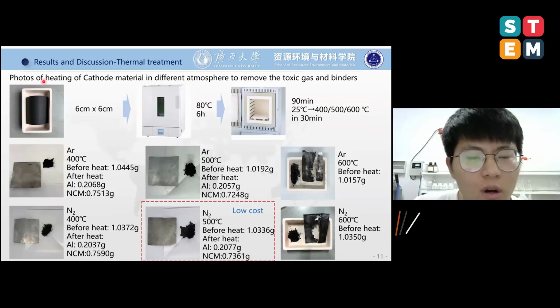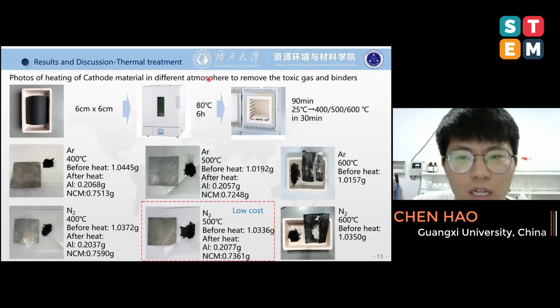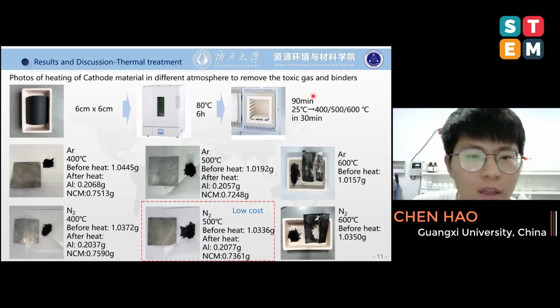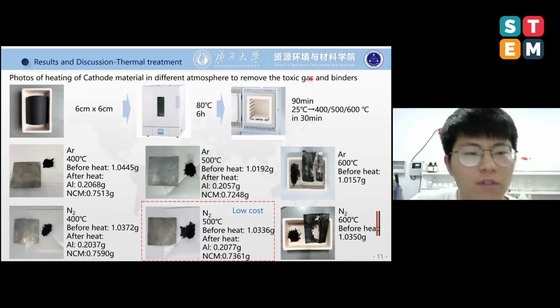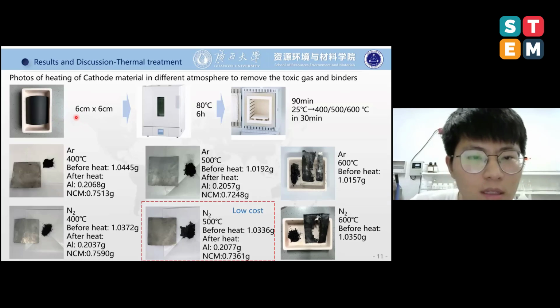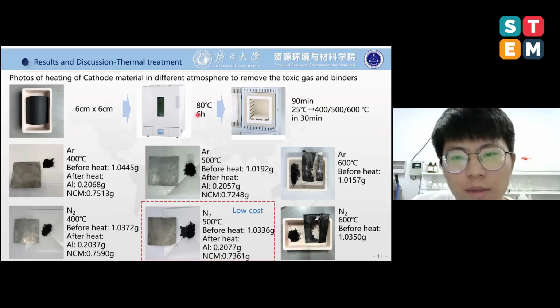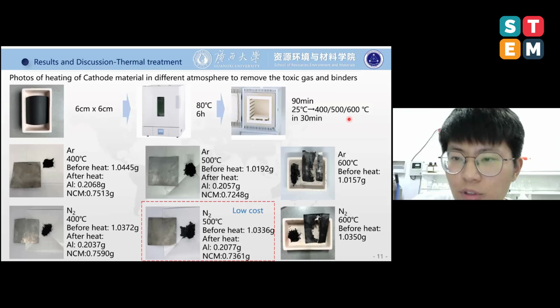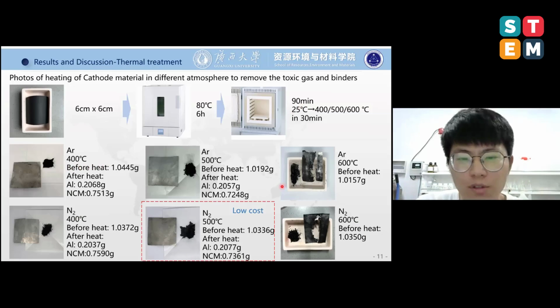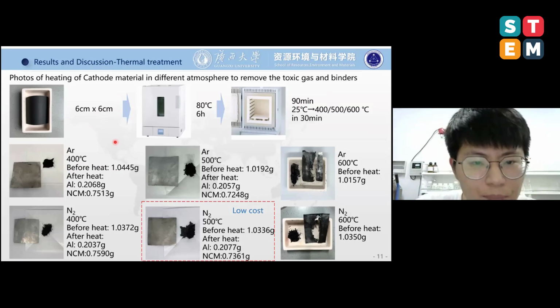And these are photos of heating of cathode materials in different atmospheres to remove the binder. First, we use scissors to cut the cathode material into square pieces of this size and put it into the drying machine for 6 hours at 80 degrees, and then put it into the furnace. We increase the temperature from room temperature to the target temperature in 30 minutes and stay for 90 minutes. These are pictures of different parameters.